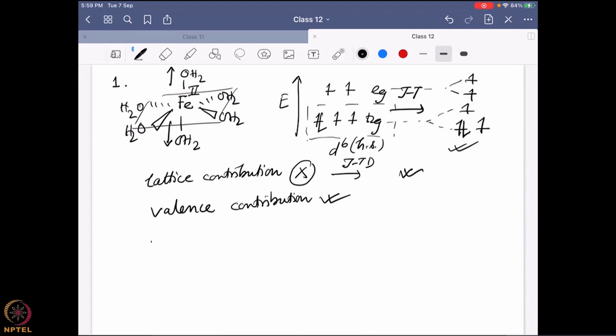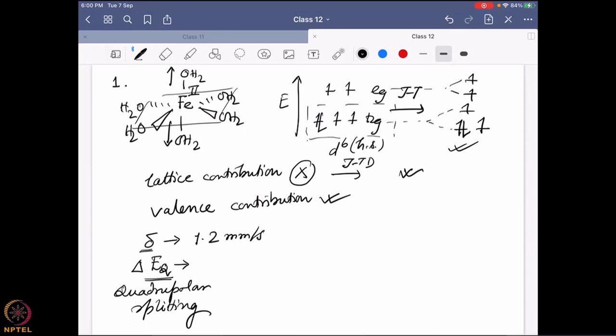So generally, once the result is shown, it is given both the values, the delta value, the isomer shift. Say it is given 1.2 millimeter per second. I'm giving you the data from the original literature. And the splitting, the quadrupolar splitting, it is written as delta EQ. And isomer shift is written as delta. This is the quadrupolar splitting. And this is the isomer shift. So quadrupolar splitting is 3.4 millimeter per second.